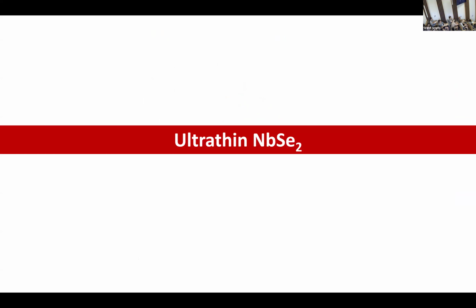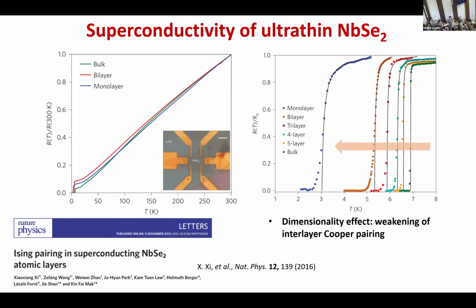So then we go to thin film. So before this work, people also try to exfoliate, but the idea was for niobium diselenide. At that time, people realized that the exfoliation works similarly as graphene, but then you cannot do it just in air because this system can degrade, the material can degrade very fast. So what they did is just exfoliate everything just in the glove box and also try to cover this whole thing with boron nitride, and then you can protect the film.